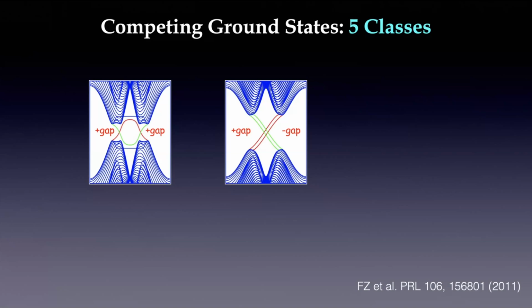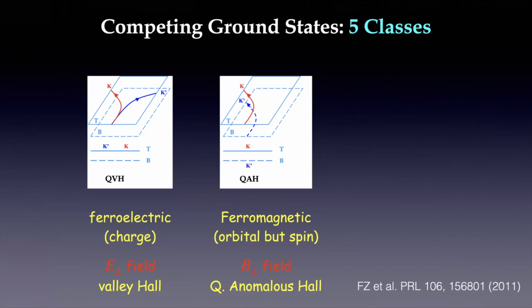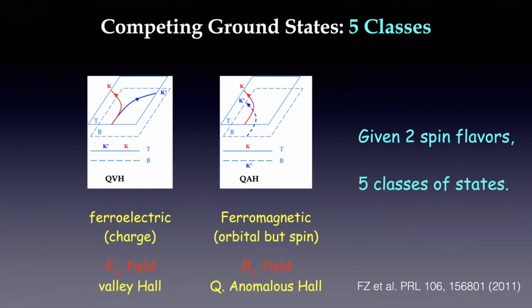So it turns out there are two possibilities if we consider two valleys. In the first possibility, all the electrons will go to, let's say, the top layer or bottom layer. So all the order parameters will couple to the electric field. Okay. In the second case, valley K goes to the top layer, valley K prime goes to the bottom layer. That is a ferromagnetic phase, and it's kind of like a Haldane phase driven by interaction. So that all the order parameters can couple with the magnetic field. Okay. So there are also two spins, right? If we consider spin, in total there will be 5 different states.